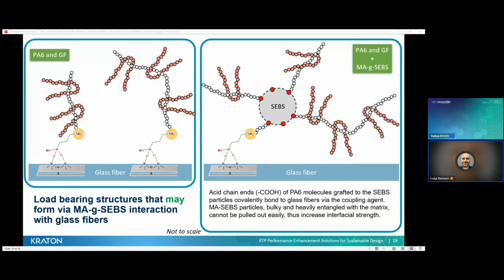The polymer molecules that are eventually grafted on the glass surface form entanglements with the surrounding melt. And this activates a very local and efficient stress transfer mechanism that boosts the tensile properties of the material. In summary, looking at the picture on the left, mechanical properties depend on the polymer glass fiber interfacial strength via the entanglements formed by the grafted molecules. More entanglements means higher interfacial strength, and this translates into better mechanics.